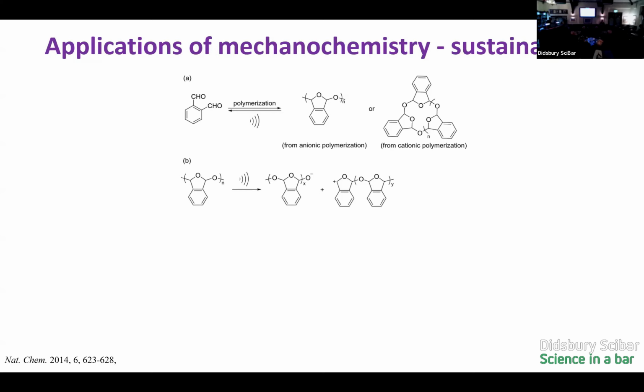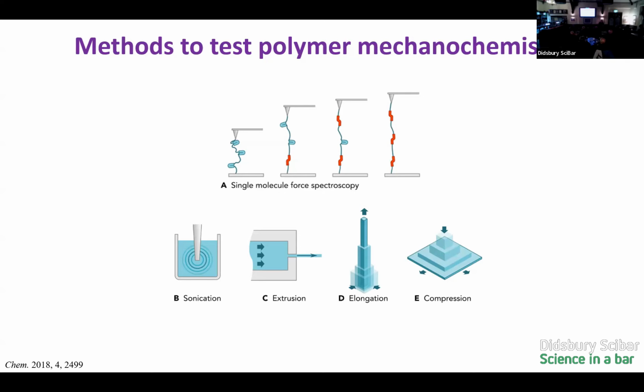The first is using AFM, or atomic force microscopy, and that's where we try to attach a single polymer chain essentially to a tip and pull it away from its surface and see how much force that takes. And that is an incredibly difficult experiment to do. You effectively have to catch a single polymer chain on a really tiny tip and make sure it stays in contact the whole way as you pull it away from the surface and measure the forces that are involved in that. And you have to do a lot of repeats to make sure you have statistically significant results, okay?